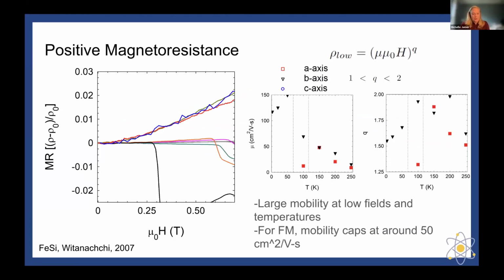So if we were to look at a ferromagnet, ferromagnetic materials normally cap out at around 50 centimeters squared per volt second. What we're seeing along all temperature ranges using our fitting model, where mu is related to the mobility, which is plotted in one of the plots to the right, is that we have a large mobility at low temperature, which is again where it's in its ferromagnetic state. The gray line notes where it enters the antiferromagnetic state, and we still have a quite large mobility for something that is not particularly magnetic at that point. What's also interesting is that if you look at the data between 150 and 250, the A and B axis have almost the same mobilities.